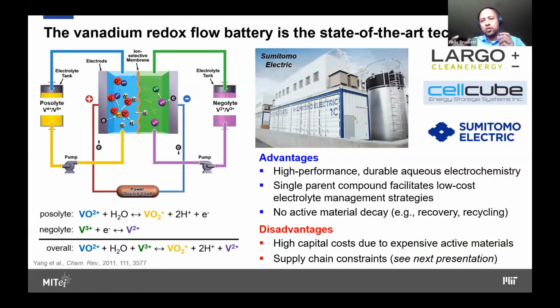And so you have vanadium 2,3 on the more negative side, and vanadium 4,5 on the more positive side. This is particularly advantageous because the ion selective membranes are not perfectly ion selective. And so it's possible over long duration operation that some vanadium ions are going to move across that membrane and interact with the species on the wrong electrolyte. If you have all of the same species on either side, though, you're based upon the same parent compound. Rebalancing or resetting the system simply involves moving solution from one tank to the other periodically. And this means that the system can be very durable and can run for a long period of time. Once it gets out of balance, we can put it back into balance by shifting the electrolyte around.